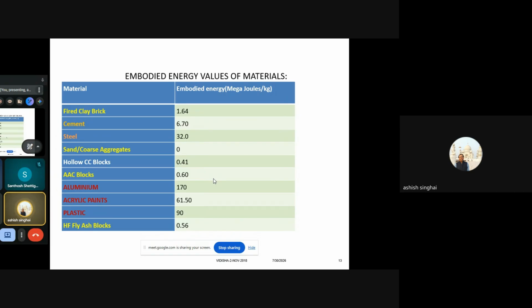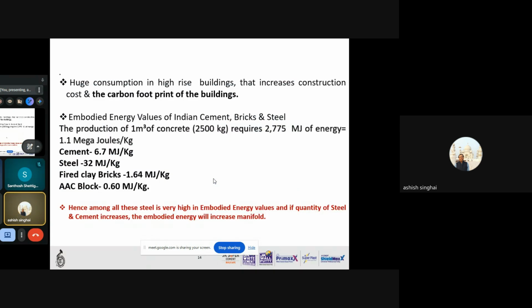Or at the same time, if we go for high fly ash volume blocks, it is almost 0.56, so almost equivalent to an AAC block. So that is a broad comparison as to, if we are given a choice, which particular cement or steel or block needs to be used on the basis of the EBE it has. Now, we cannot skip cement, we cannot skip steel. It has to be there, but there has to be judicious selection and judicious structure designing wherein we can minimize the consumption of cement, reduce the steel requirements, or possibly replace it with some befitting options or alternates.